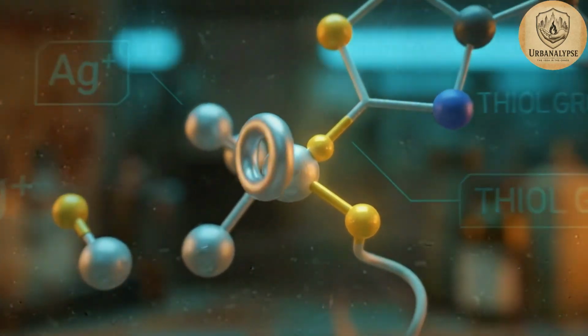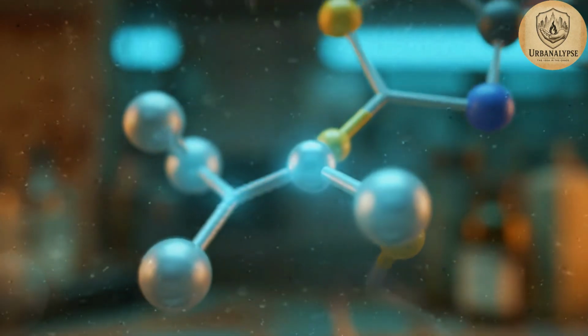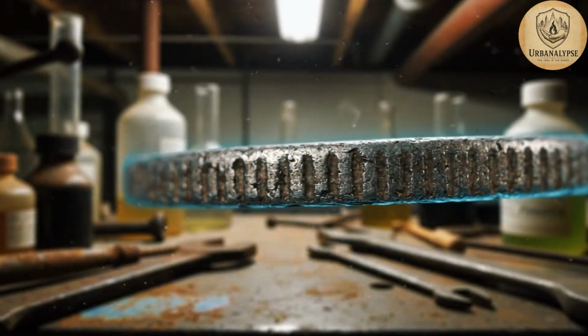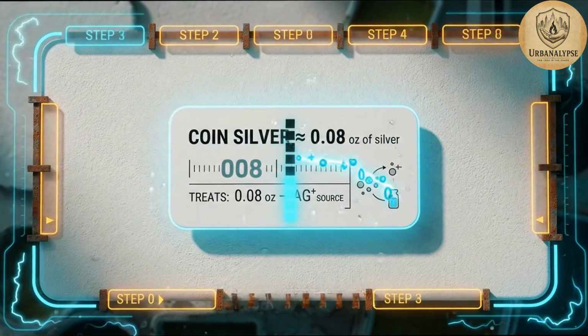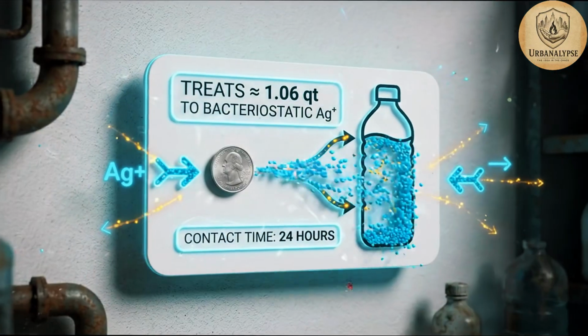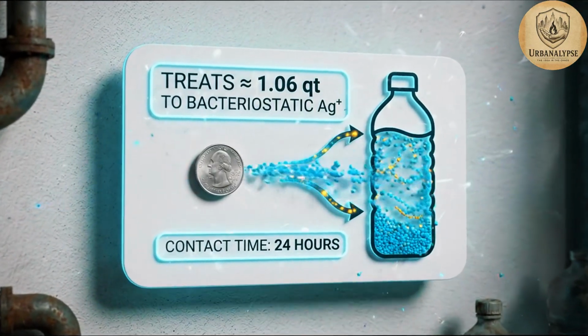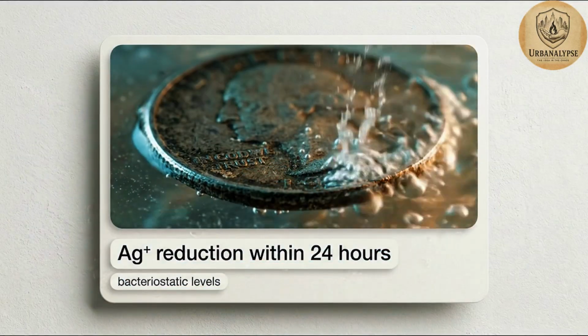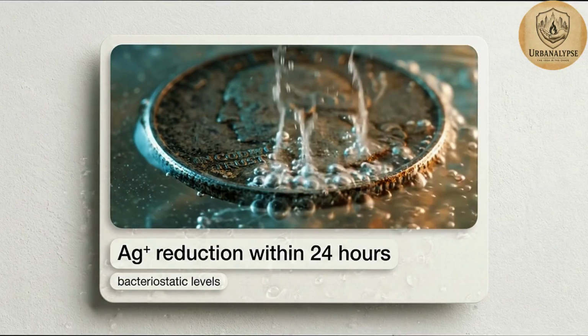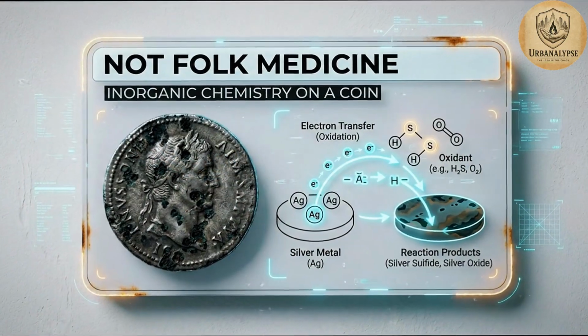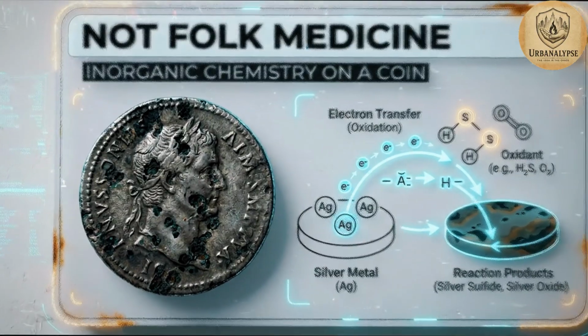The physics hasn't changed. Ag+ still binds thiol groups. It still denatures bacterial enzymes. A pre-1965 US dime contains approximately 2.25 grams of silver, sufficient to treat a 1-liter container to bacteriostatic Ag+ levels within 24 hours of contact time. That's not folk medicine. That's inorganic chemistry running on a coin.